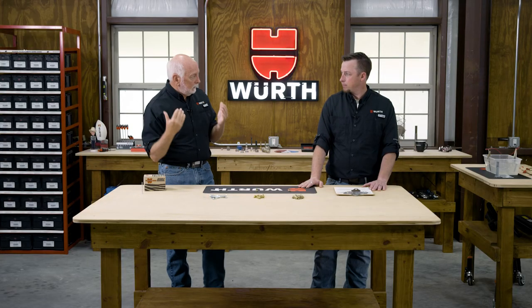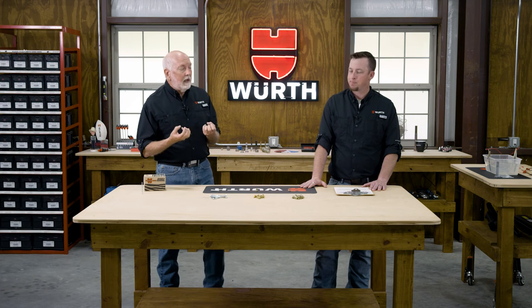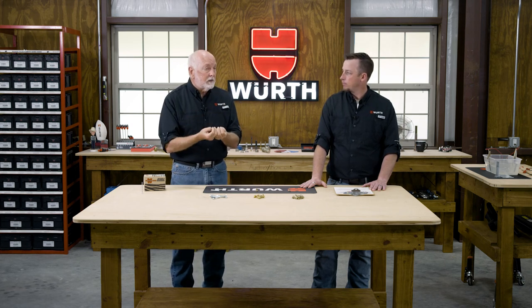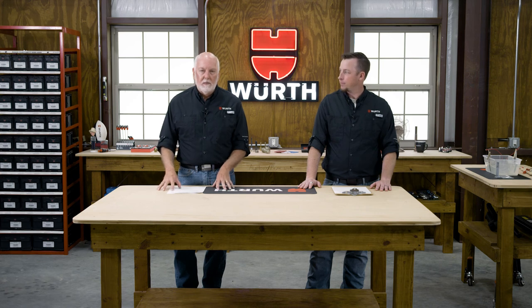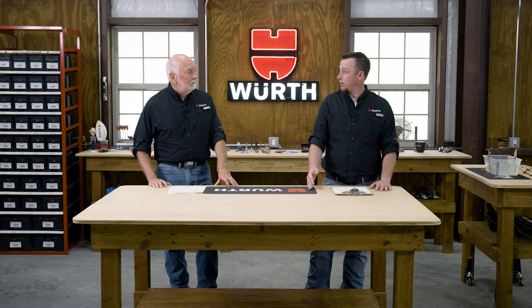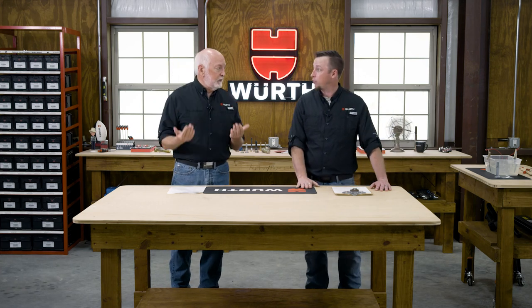So then we came up with putting a sealer on top — a third layer of protection. These are silica-based sealers and the idea is that they're hard and more scratch resistant. We found that works very well depending on the geometry of the part and the packaging and handling. For a lot of fasteners that works well. The extra sealer also gave a lot of extra corrosion protection. In conclusion, the world has been turned upside down on electroplating due to environmental concerns with hexavalent chromate. A lot of customers are trying to figure out what to do. If you're using hexavalent chromate, you have to know if it's restricted where you're using it. And if you've had to make a switch to trivalent, you may have to do some things to overcome the loss of corrosion protection — like that additional sealer.